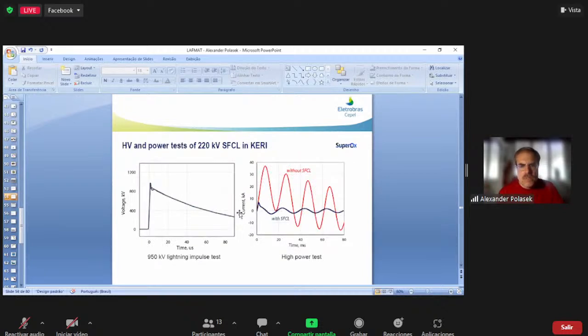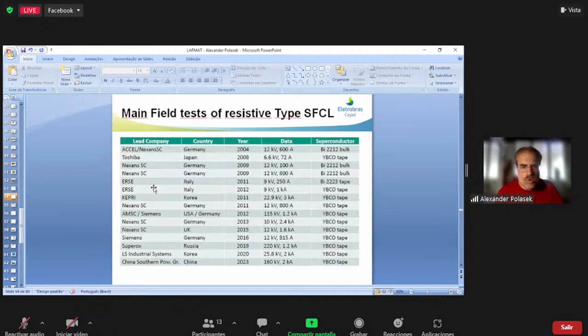And in some tests, you can see the red curve without the fault current limiter, and the limitation is amazing, the limitation of the fault current using the superconducting fault current limiter. And also high voltage tests to test the insulation, another critical point. All equipment for high voltage requires high voltage tests, because the insulation is critical. If you don't have a good insulation, and insulation for cryogenic temperatures, it won't work. These are the main field tests of resistive type SFCL. As I told you, there are other kinds of fault current limiters.